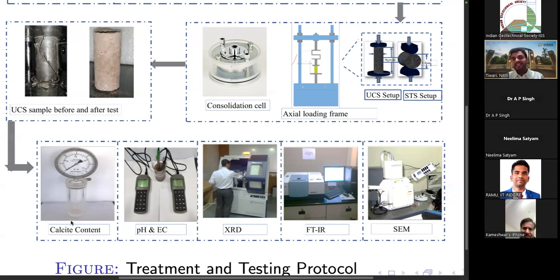And these are the facilities which are available in our area neighborhood, like IIT Indore. They have very good facilities for these kinds of tests. So let me talk a little bit about every test. The calcite content test is very small equipment, like people can have it at their institute also. And we just check how much calcite content is present once you do the testing. pH and electrical conductivity are also responsible. pH is very important for your cementation effect. So we need to maintain the pH in the treatment process, and electrical conductivity just indicates whether the chemical reactions are taking place or not. So we need to think about it.